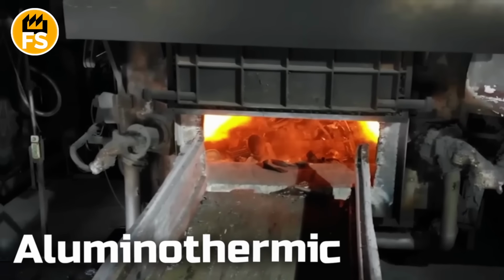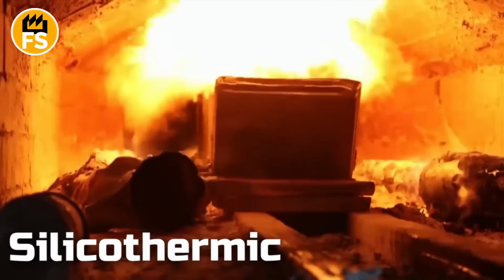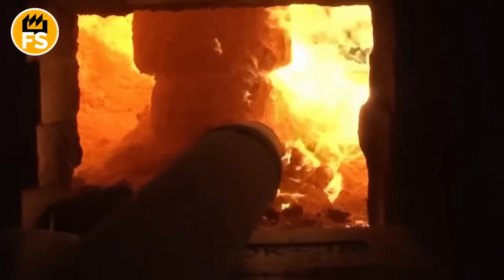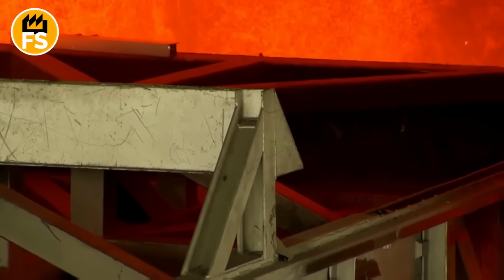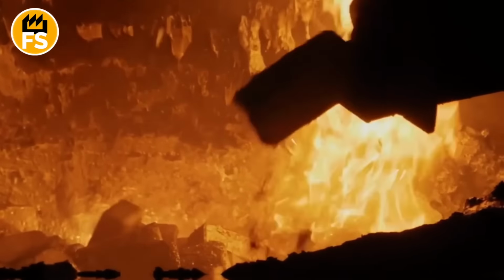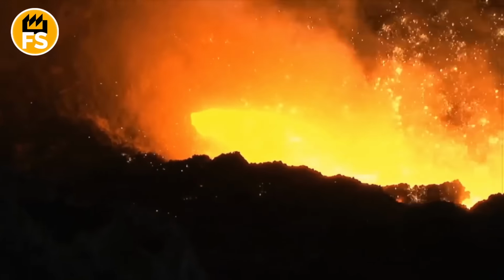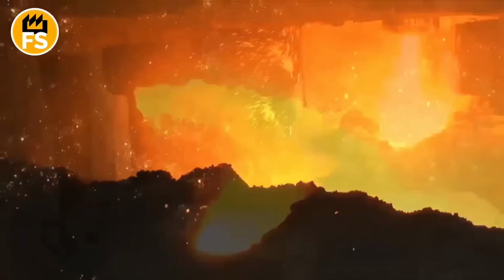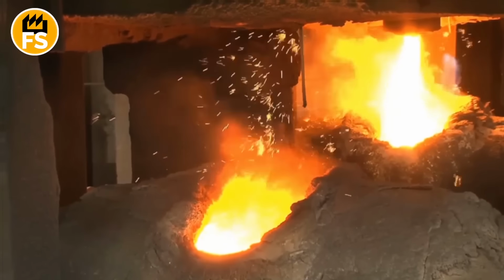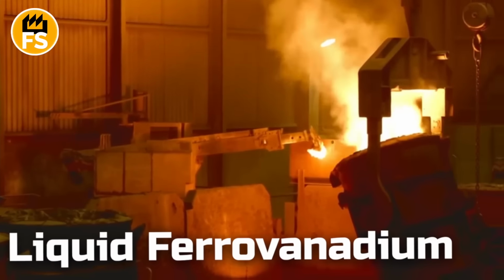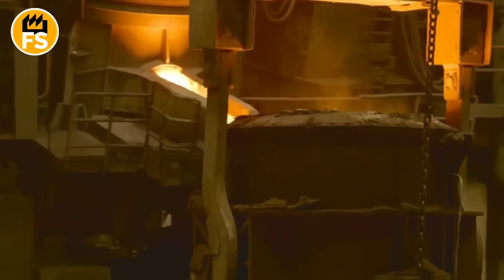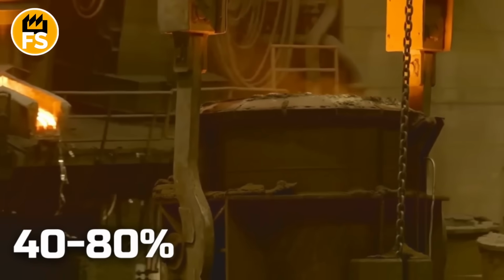During aluminothermic or silicothermic reduction, the reaction proceeds extremely rapidly and releases a significant amount of heat. Vanadium oxides surrender their oxygen to the reducing agent, while pure vanadium transitions into a molten state and immediately dissolves in the iron. The result is liquid ferrovanadium with a specified metal content, typically ranging from 40 to 80% vanadium, depending on customer requirements.